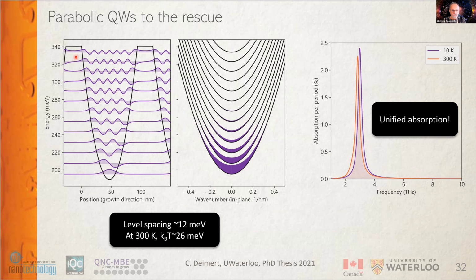and one candidate which looked particularly promising are parabolic quantum wells. As you may remember, in the parabolic potential, the energy levels are equally spaced, and this, of course, gives us the chance that as we increase the temperature, we are not going to see splitting of those transitions. They will just add up, and they do. Okay, so this is unified absorption. In fact, what we are seeing is the formation of the multi-subband polariton. All of them kind of get together.